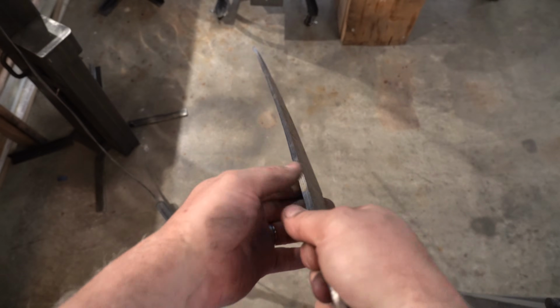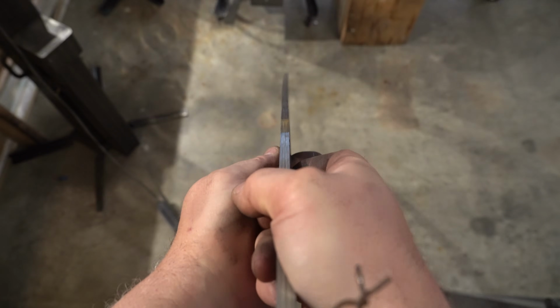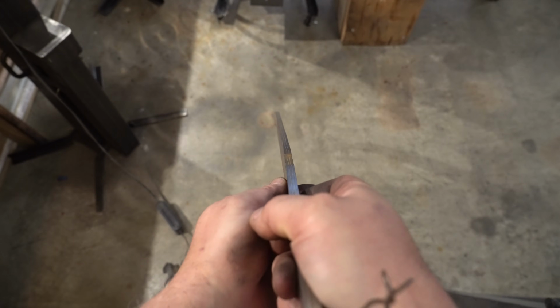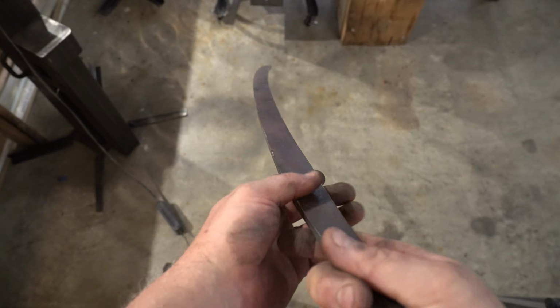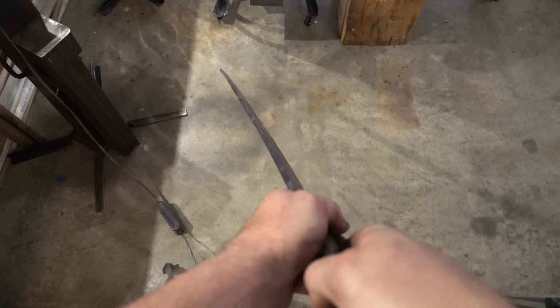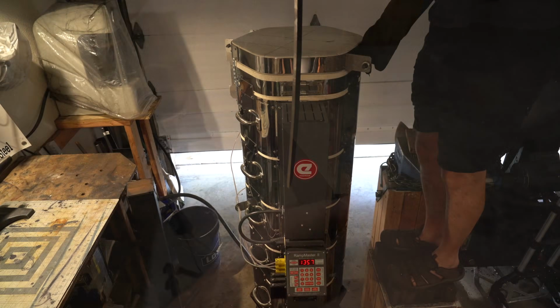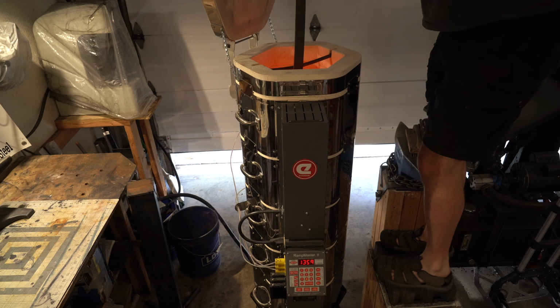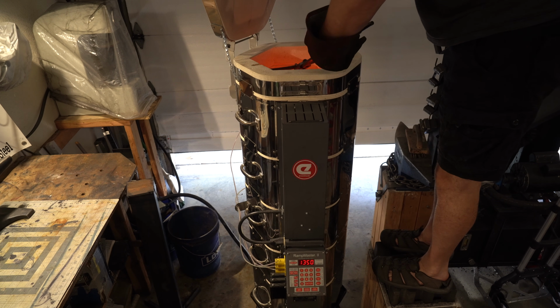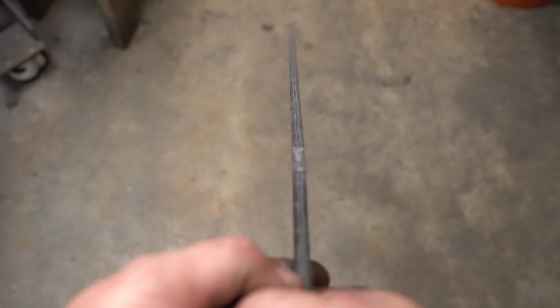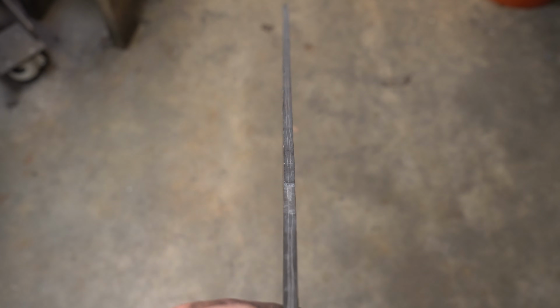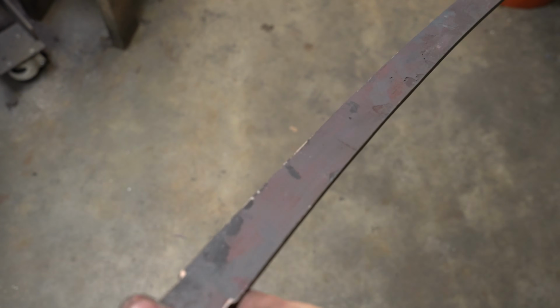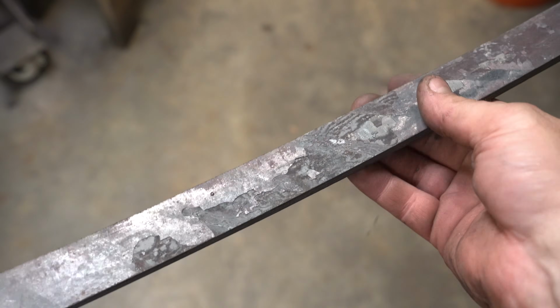So now the only issue I have is I didn't get it exactly as straight as I wanted while forging. So I'm going to put it in the new heat treating oven and normalize it and actually straighten it out at the same time. This is a 47-inch vertical heat treating oven from Even Heat. It made the whole heat treating process much simpler. So during the normalization cycle, I just threw this in the press quickly and it is dead straight now, which makes me happy. Now I'm going to surface grind the edges, and then we'll start our bevels.